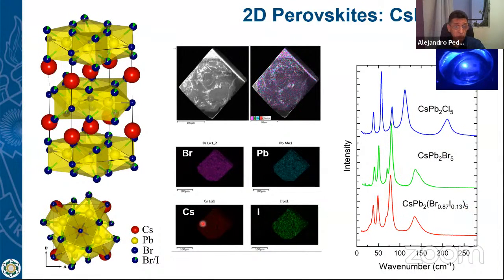The bromine and iodine are completely distributed in the sample, but when we determine the structure by single crystal X-ray diffraction, you can see that the iodine is only localized in this part of the structure. It is not substituting these atoms. Okay.